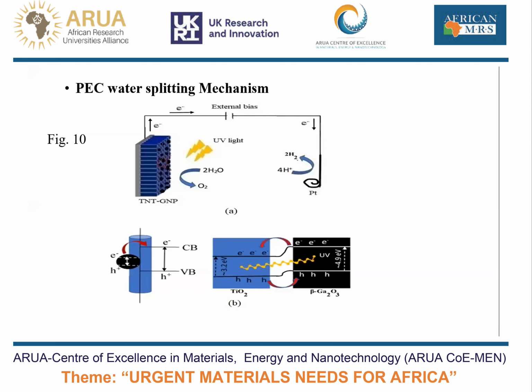Now, the water splitting mechanism is as depicted in figure 10. Because the nanoparticles are in contact with the nanotubes, when the material is illuminated with UV light, the electrons and holes are excited, and then the electrons are transferred from the gallium oxide into the conduction band of the titanium oxide, while the holes from titanium oxide are transferred to the valence band of the beta gallium oxide. So the built-in field at the interface now boosts the charge carrier separation and transport towards improved water splitting properties.